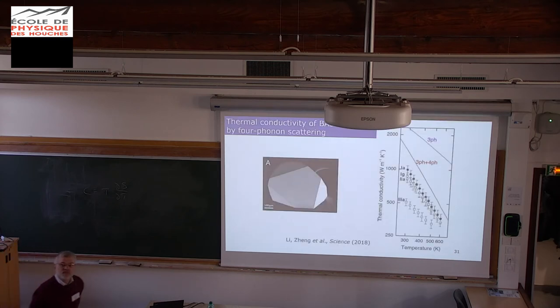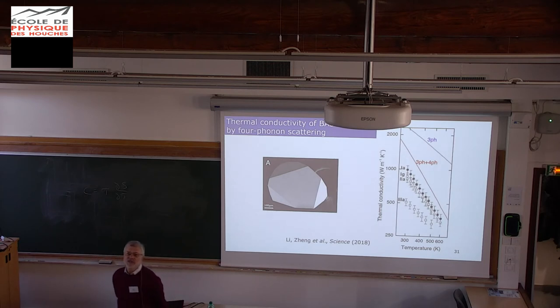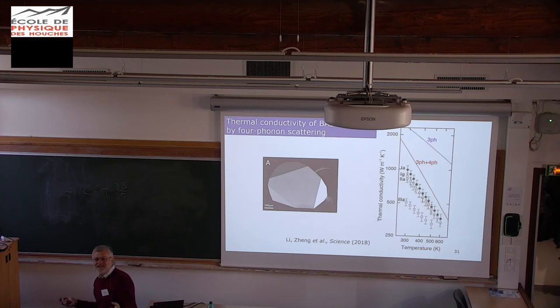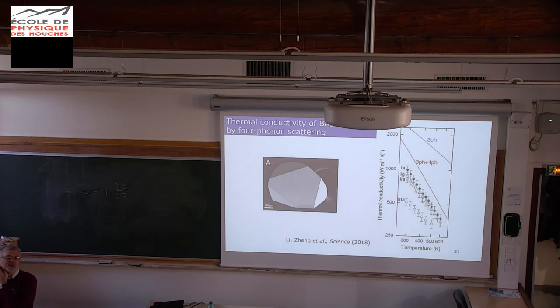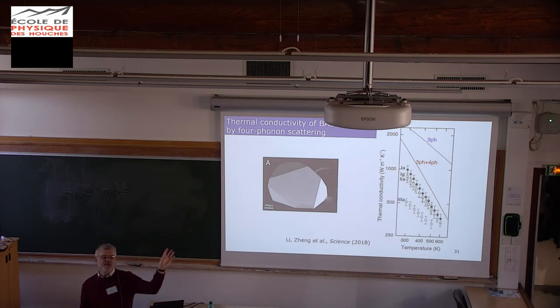The three-phonon calculations are pretty general now — codes are available online for your favorite crystal, up to some complexity. The four-phonon scattering codes available are currently limited to cubic crystals with two atoms. For diamond, three phonons are sufficient, probably because there's no big gap between the optical and acoustic phonons, similar to silicon. Gallium nitride is somewhere in between: at room temperature three phonons is enough, but at higher temperatures you need four phonons. It's becoming more understood that optical phonons play a large role in scattering acoustic phonons to an extent that wasn't previously appreciated.